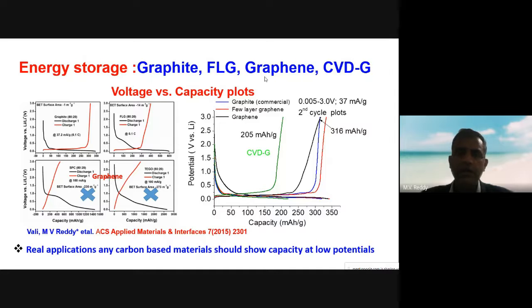Again I'm repeating graphite and graphene. Usually carbon-based graphite is more popular because of its lower discharge potentials. If you talk about graphene and graphene-type materials, you may get higher capacity. Practically, though, this type of material may not be really useful for practical systems because the voltage is not matching. And these are a few examples with CVD, chemical vapor deposition, grown graphene.